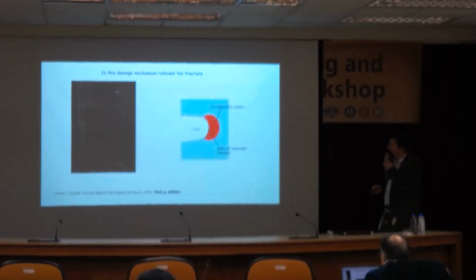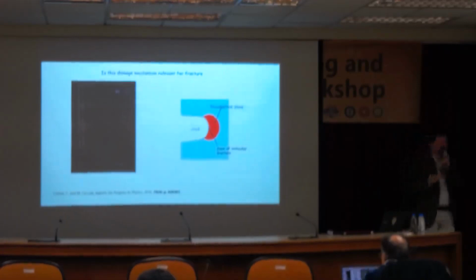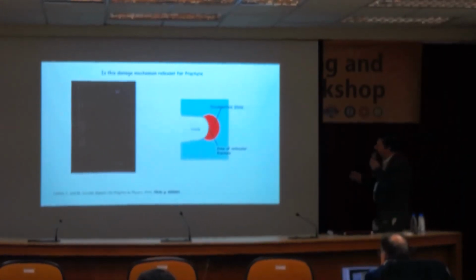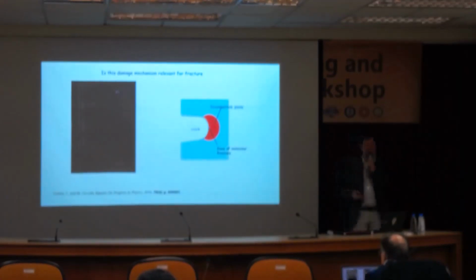So how is this now relevant for fracture itself? Because this is just linear extension. So if I look at fracture, what we want to know is really where are we breaking bonds in front of the crack, because this is what really causes it to move. And one of the hypotheses is that these sacrificial bonds actually slow down crack propagation, and so that tough material would have more broken bonds in front of the crack tip.